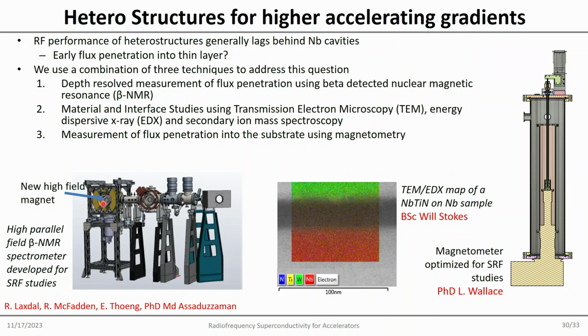So you want to see whether there is really flux entering. Then the second is, of course, you want to correlate that to your material, see if there are cracks, however your material looks. For that, we can use transmission electron microscopy combined with the EDX technique, which tells you about the elements. So this is how it looks. This is a very good film. As you see here, the layers are well separated: niobium titanium nitride on niobium, well separated. On the top is just a protective layer.